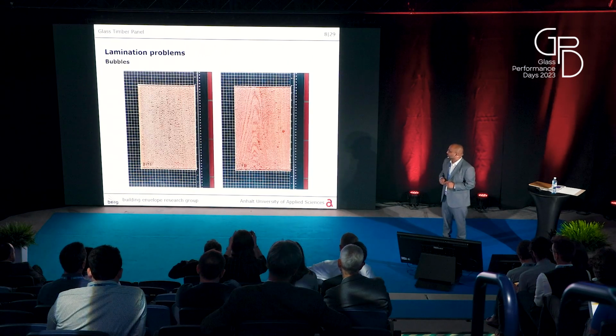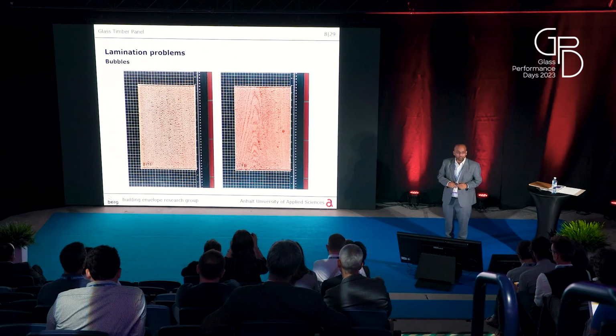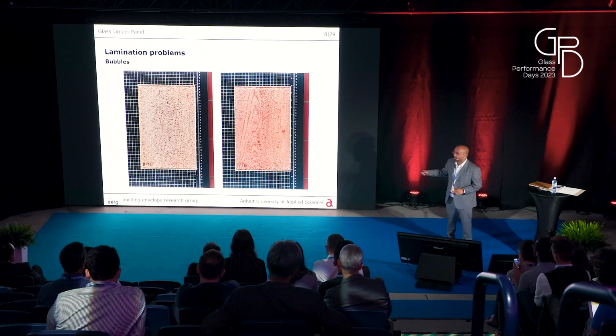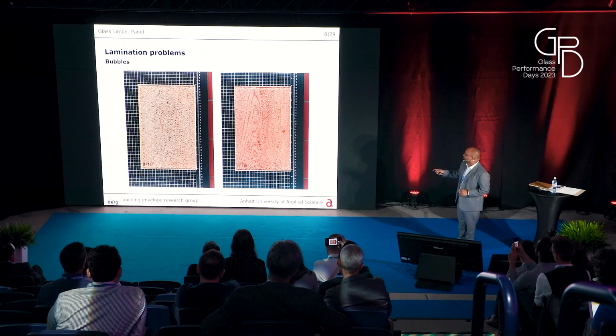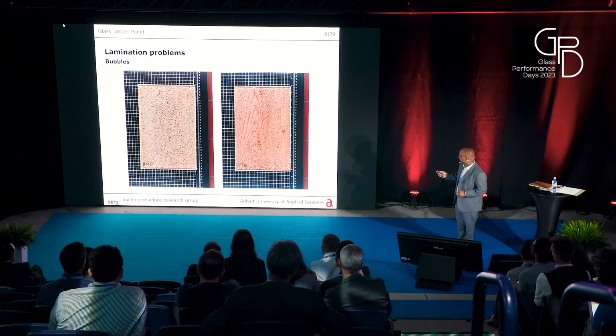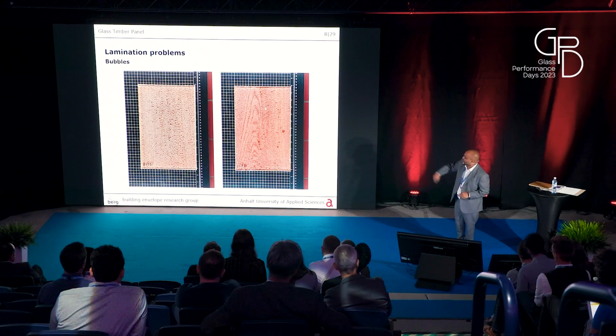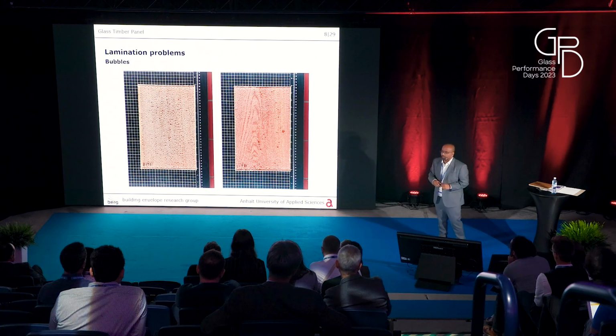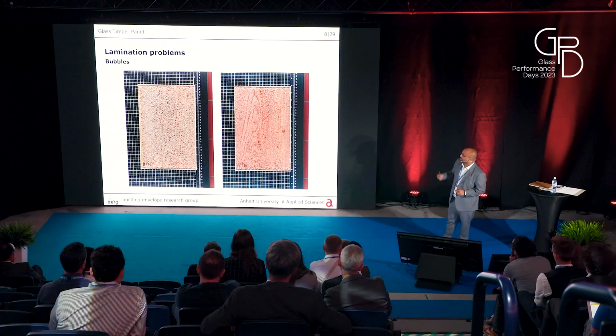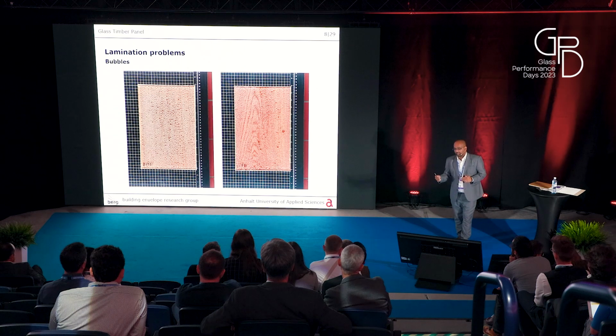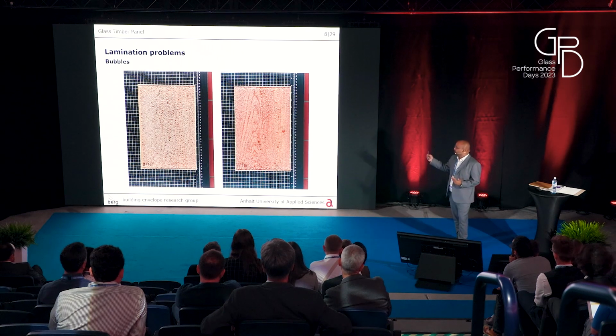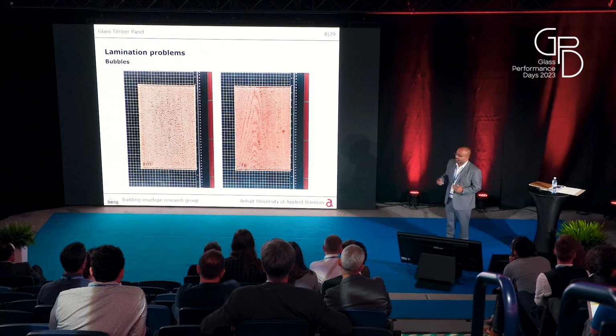And then bubbles. Although my project partners really liked the example, we don't want to use this. We can see how the bubbles orient themselves around the fibers. It was mostly due to insufficient heat developed in the interlayer, because the interlayer didn't melt properly.